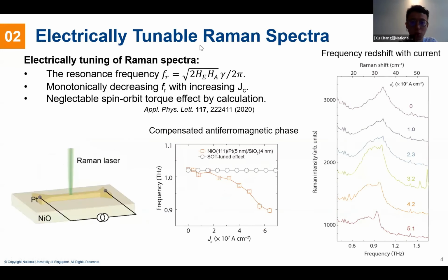Then we have shown electrically tunable Raman spectra in this nickel oxide single crystal and platinum heterostructure. We have deposited this platinum wire on top of a nickel oxide 111 single crystal, and then we measure the Raman spectra at the center of this device. The resonance frequency can be calculated as a function of the exchange field and anisotropy field. The frequency at room temperature with no current is around 1 terahertz.